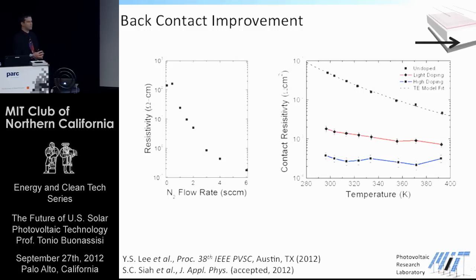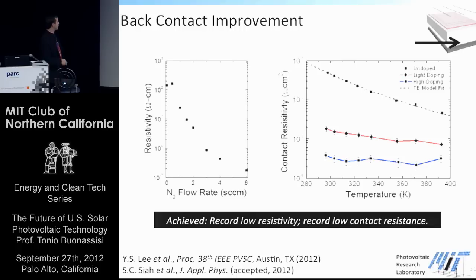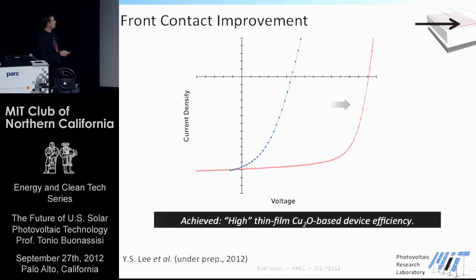So this shows a systematic approach. In your mind, you can hear the timer going: 1 year, 2 years, right? You can see the publication dates down here progressing. So we achieved record low resistivity, record low contact resistance. Now, this layer up here, the front contact, improving the front contact boosts the device performance quite a bit. These are all in arbitrary units. You can think of these curves as the bigger the curve, the better. And this is a so-called high-efficiency thin-film Cu2O-based device. We're not plotting specific numbers on here just yet, but that hopefully will be coming out soon. And you can see a systematic approach being taken to improve the device one step after another.